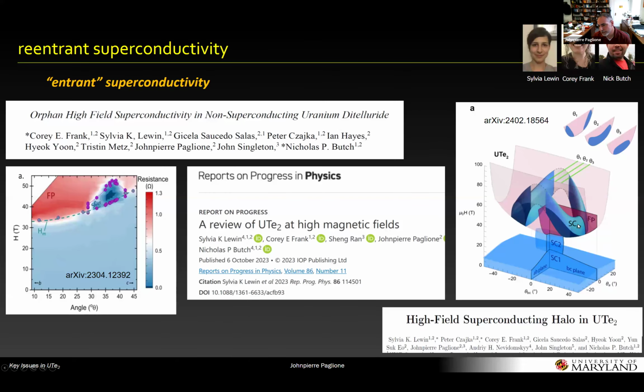Okay, so one thing to note about this, and if you look in this paper for more details, you can find there's some work by Andrei Nevedomsky, just a simple model, trying to understand the implications of the shape of this superconducting phase. And one thing to note is that this is non-monotonic, of course. So you can see over here, for instance, this upper critical field goes up and then actually comes down. And this is actually quite hard to understand just from a free energy model for a single component order parameter. So just to note in passing, this already implies that this phase perhaps may be a multi-component order parameter phase. And then, of course, as you tilt the field away, there are even more interesting sharp features that evolve that probably need even more complicated explanation.